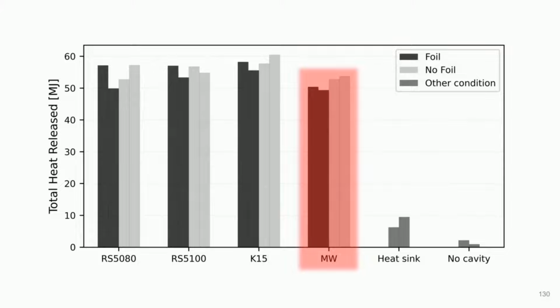And much the same result for the mineral wool insulation, although in this case there is slightly less total heat release. So you can see those bars are all slightly lower than we get for the polymer foam insulations, probably because this insulation contains very little fuel to release in the first place.